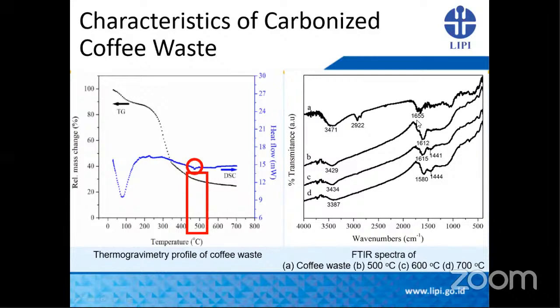But if we compare the FTIR spectra of coffee waste and the carbonized sample at 500, 600, and 700 degrees C, we can see here for the sample carbonized at 500, 600, and 700 degrees C, there is no significant difference. So we can just use the lowest temperature, which is 500 degrees C for carbonization.